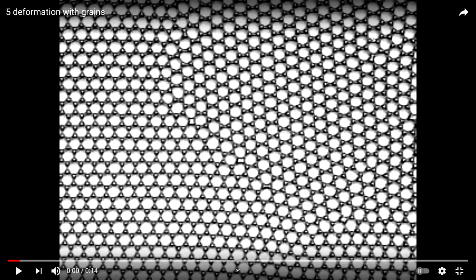So that dislocation I was talking about, it's up here in the upper right. It looks like these 4 atoms. And it's not the world's greatest movie, but see if you can follow what happens. This dislocation is going to travel sort of down and to the left. And I'm going to play the first part of this very slowly at first, and we'll speed it up to normal speed. Let's just keep an eye on it. It's very slow, but now it's traveling down. You can see a bit of a deformation along this line. Keeps going. Hits the grain boundary. The atoms aren't aligned correctly anymore. Nothing happens.